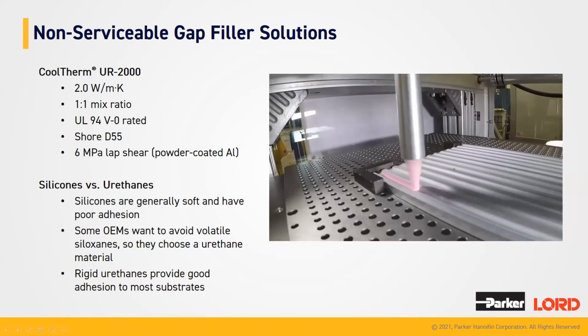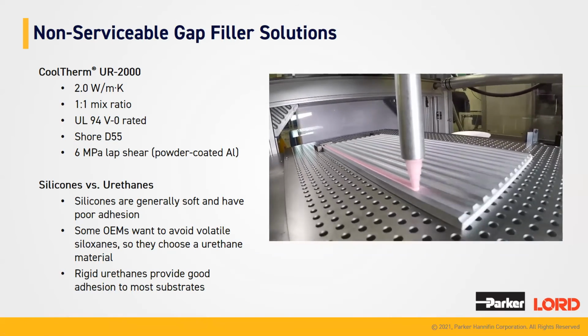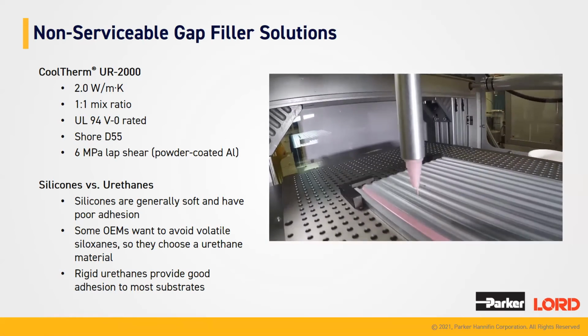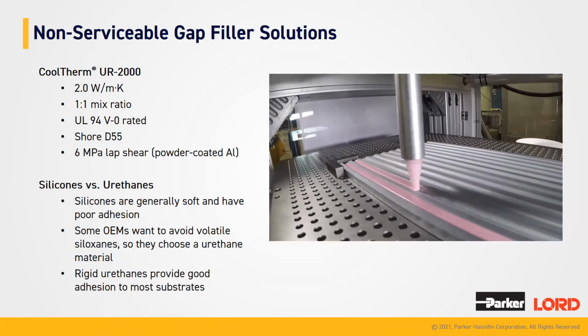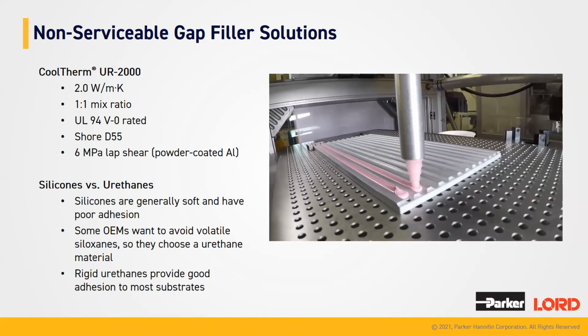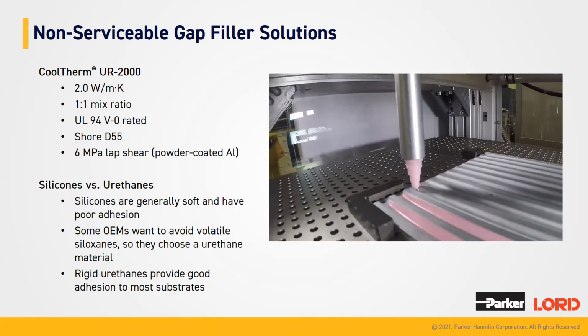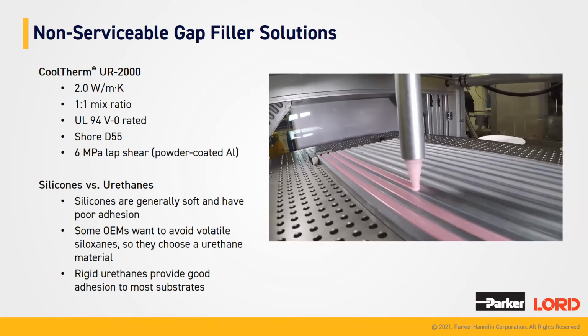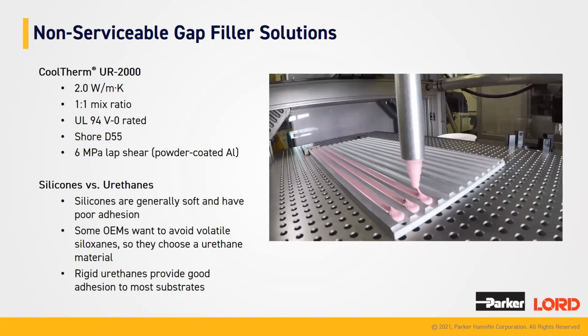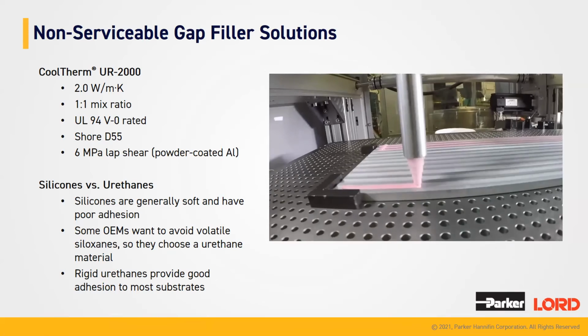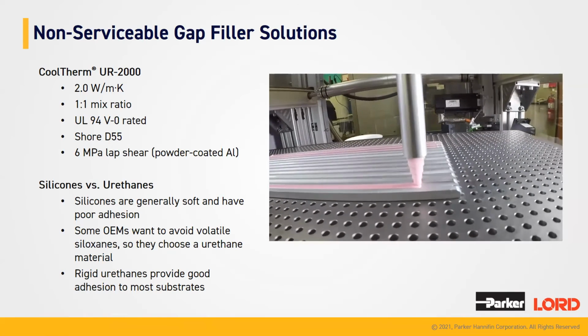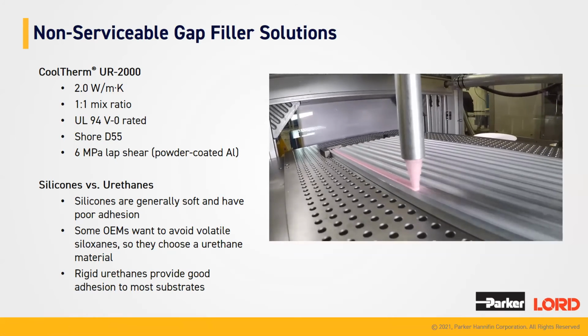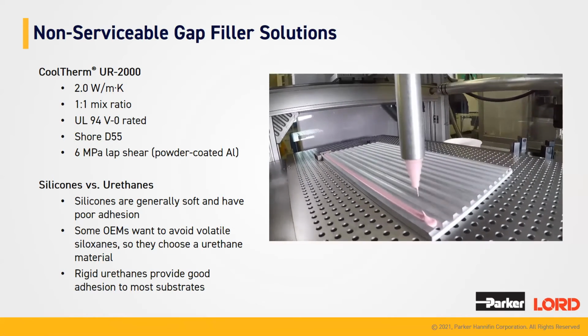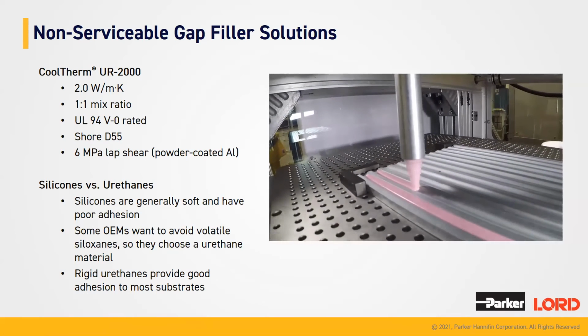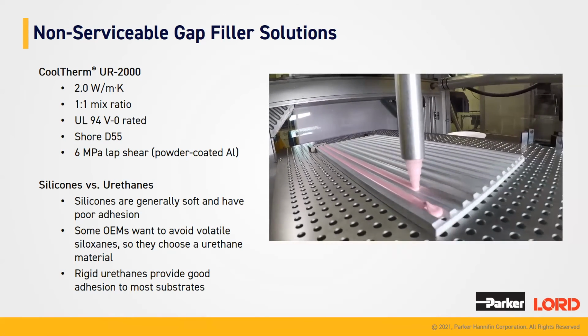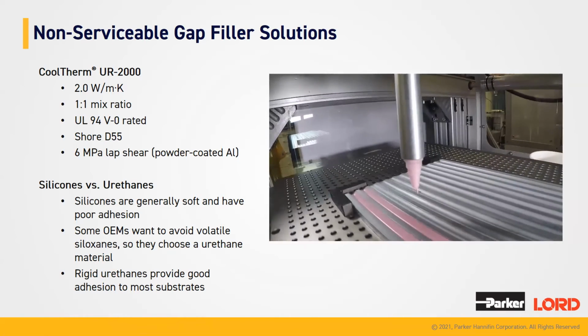We're seeing urethane gap fillers pick up traction as being more popular in EVs, especially in the non-serviceable solutions, because urethanes generally have better adhesion than silicones. And in addition, urethanes do not produce volatile siloxanes. Now, volatile siloxanes have the reputation of preventing the adhesion of coatings or paints or other adhesives to the substrates that they should be attached to. So by eliminating the potential for volatile siloxanes to be present in manufacturing processes, urethane gap fillers just give OEMs more comfort. And we'll talk more about this in trend number 4 later on in the presentation.